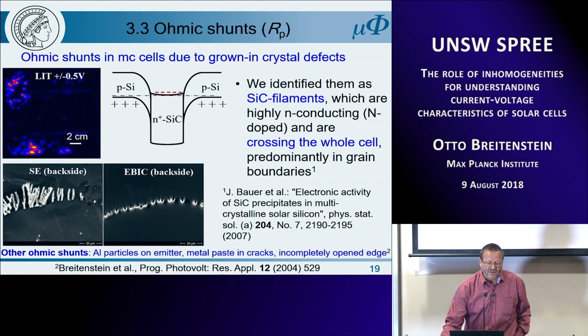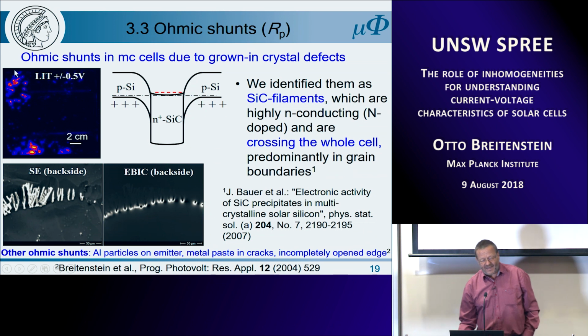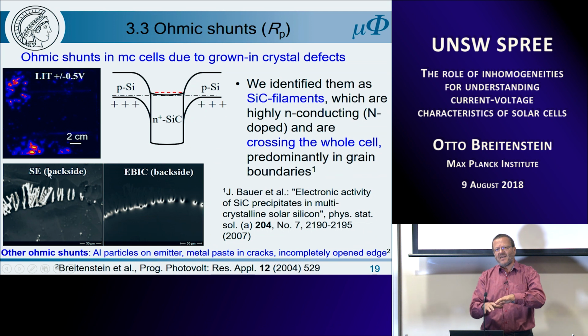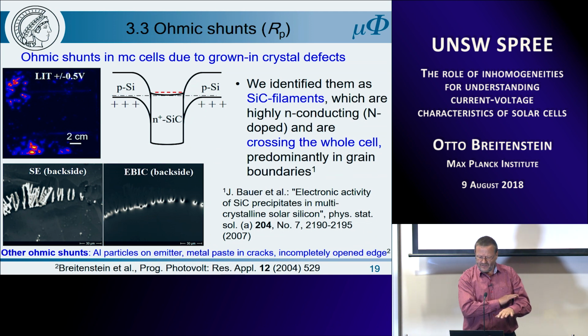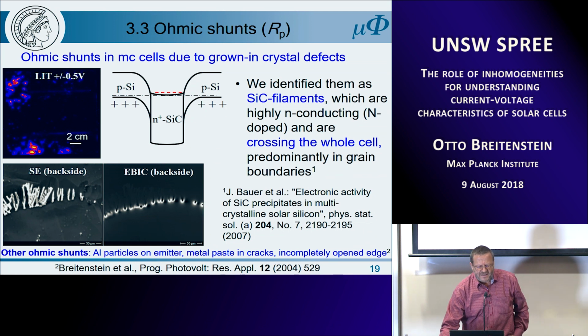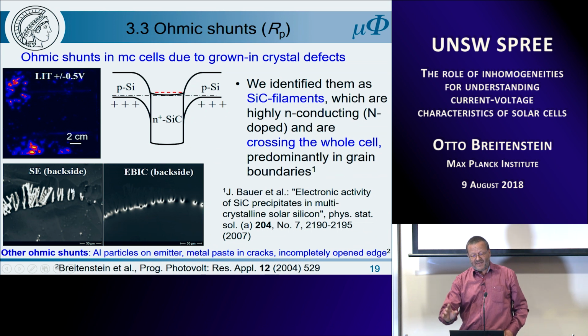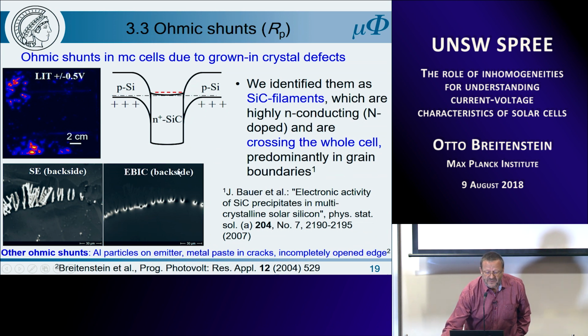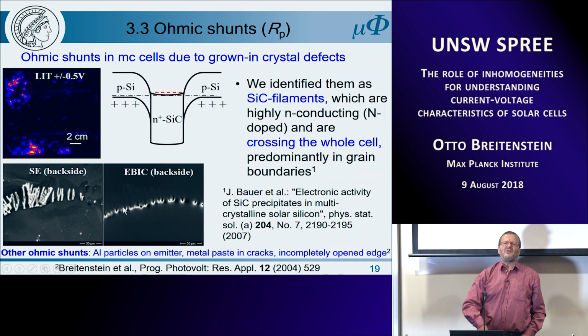And this is how it looks in lock-in thermography. If we have the same image at plus minus 0.5 volts, then it is an ohmic shunt. And if we have prepared from the back side, we have dissolved some material in HNO3 and did not wipe. Then they come out, and these are these silicon carbide filaments. And if we make EBIC at the back side, we see that if the beam comes close to these things, we have a collection efficiency close to 1.